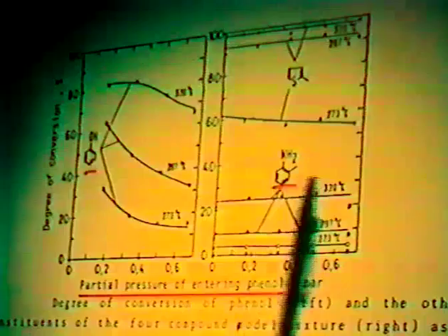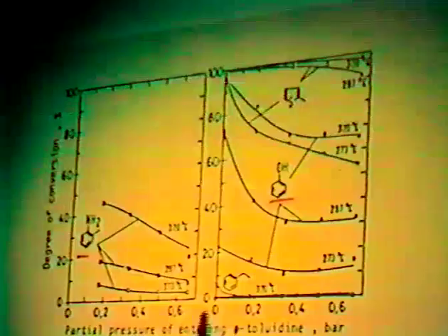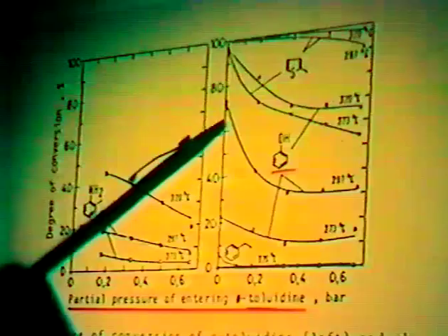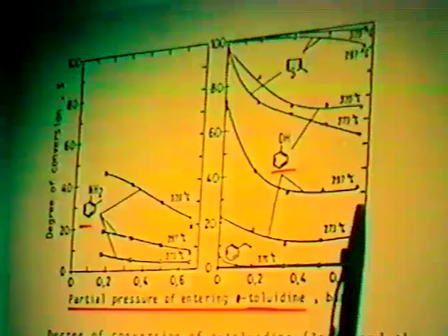Whereas when making the same experiment with change of the concentration in the feed of the p-toluidine, the degree of conversion of the phenol is seriously affected and decreased, so that this shows strongly the inhibiting effect of the p-toluidine on these sites, which may have more affinity compared to that. And so far, this is a strong effect in the system as well.